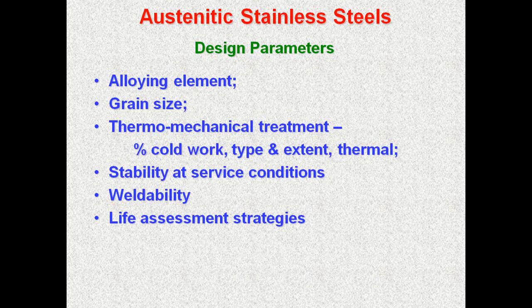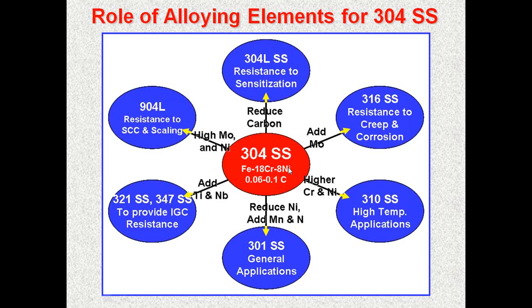If you look at the alloying elements, you take the basic 304 stainless steel, which is very popularly known as 18-8, that is 18 chromium 8 nickel stainless steel, which contains between 0.06 to 0.1% carbon. One can play with this composition to get various types. For example, if you reduce the carbon to eliminate the problem of sensitization and intergranular corrosion, you get 304L stainless steel. If you add molybdenum to this, about 2.5%, it becomes 316 stainless steel, which has a lot of resistance for creep and pitting corrosion.